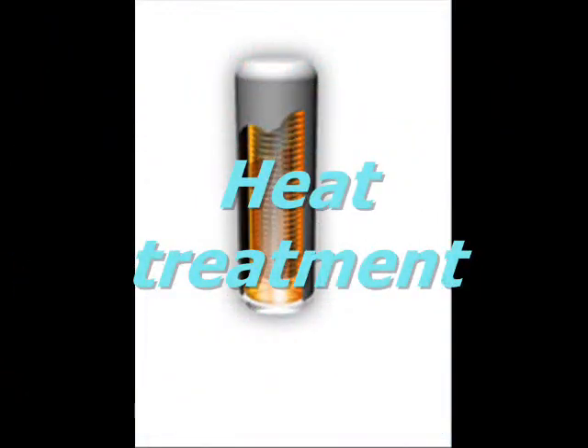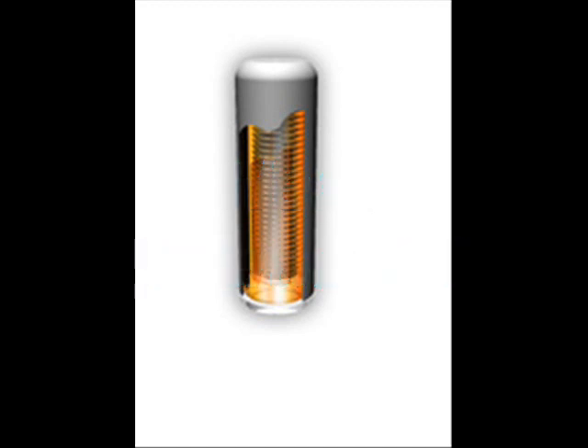Heat treatment to remove unstable donors. Heat treatment is applied in a diffusion furnace. Oxygen-derived unstable donors n-type impurities generated during crystal pulling are decomposed in order to restore the originally intended specific resistance.